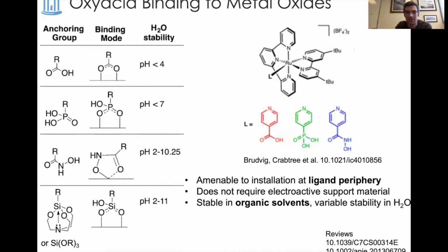So these silicon linkers, there's a lot of different precursors you can use. One example from which I pulled this table looks at silatranes that are convenient because you have a quite stable silane reagent that's relatively bench stable, but you can still form a robust linkage to the surface.